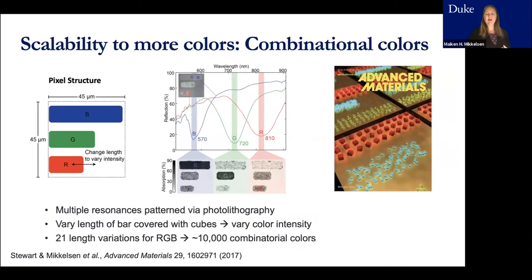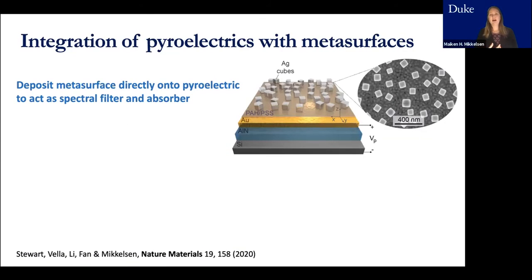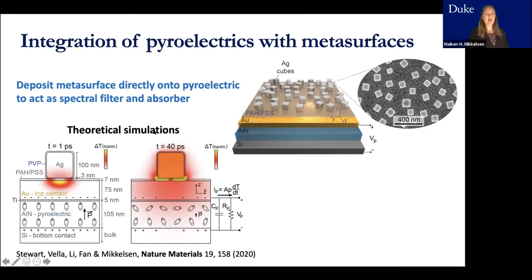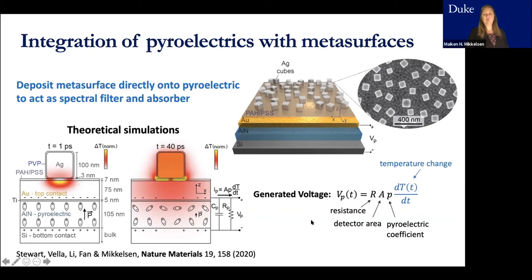So now that we have a way of making spectral filters, we want to integrate that with pyroelectrics. What we're doing here is depositing a metasurface directly on top of a pyroelectric material, in this case aluminum nitride. And here you can see from some simulations how the heat is moving in the structure, 1 picosecond after excitation. We mainly have heat generation in the gap, but then it's diffusing down into the pyroelectric layer underneath, changing the polarization and causing a voltage. And this generated voltage depends on the resistance, the detector area, the pyroelectric coefficient, and the temperature change.